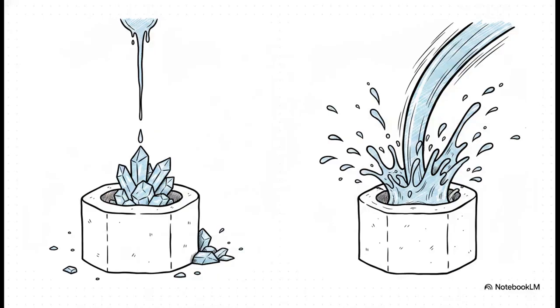Now, what's really interesting here is that finding the perfect pouring rate is a total Goldilocks scenario. It has to be just right. If your volumetric pouring rate is too slow, the metal chills. It loses all that superheat way too fast and freezes before it even finishes filling the cavity. But if you go too fast and your rate is excessive, well, you trigger violent turbulence. And that leads us straight to our third villain.